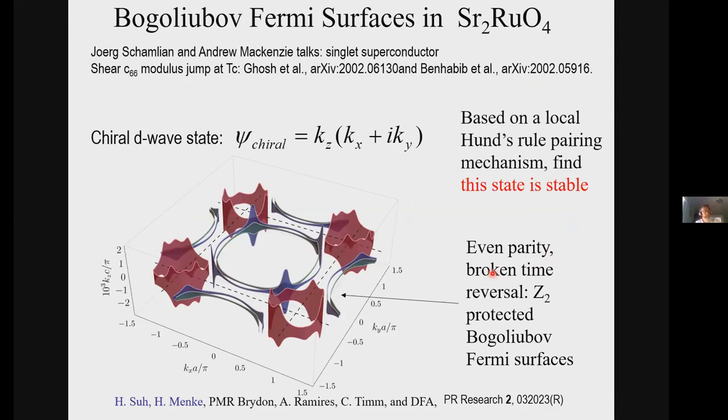Yeah, that's an excellent question. The one thing I didn't emphasize in the talk, and maybe I should have, is the scale of my c-axis momentum here in reciprocal space. If you look, this is 10 to the minus 3 times the c-axis reciprocal lattice vector. And this tells you that along the c-axis, this takes up something like 1% of the Brillouin zone.